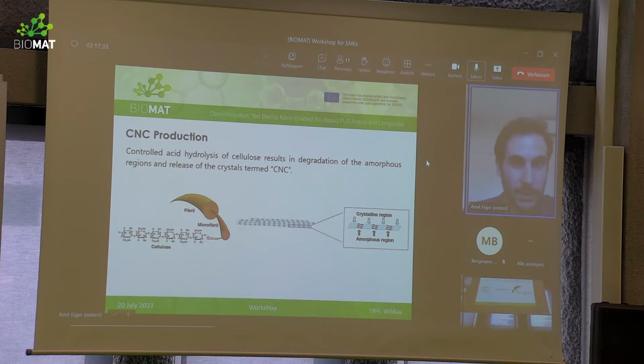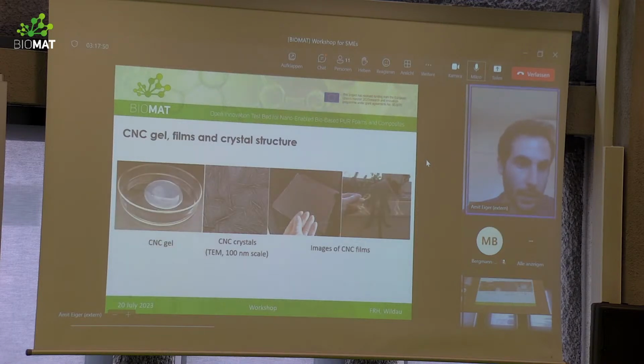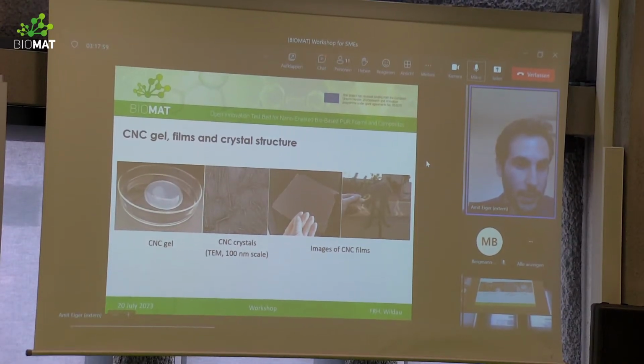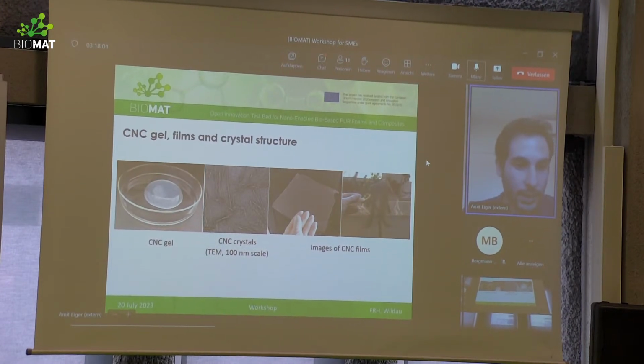About CNC production, controlled acid hydrolysis of cellulose leads to degradation of the amorphous regions of the cellulose and to the release of the crystals termed CNC. As shown here, produced CNC is in water suspension or gel form. The crystals have a rod-like structure, and when they are dry, they can form a very nice transparent film with very interesting properties.